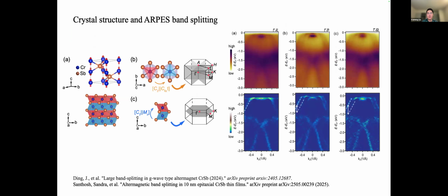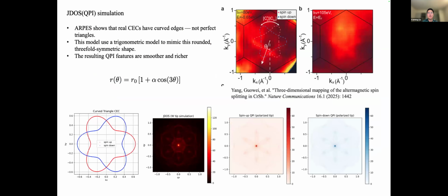So let's take a look at the chromium antimony structure. The chromium antimony has a layered structure. The two chromium sublattices are related by rotational symmetry, which breaks the time reversal symmetry without net magnetization. And this leads to altermagnetism and causes momentum-dependent band splitting. On the right, the ARPES data shows clear band splitting along different directions, especially visible in the second derivative maps. So this is a model.